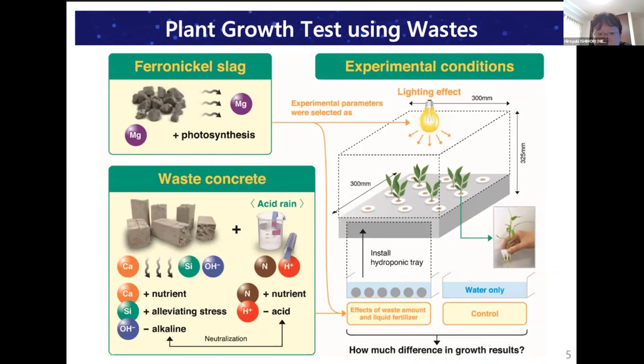Ferronickel slag has a lot of magnesium, which enhances photosynthesis. And waste concrete has a lot of calcium and silica as nutrients. Also, a lot of alkaline is included, so acid rain is co-used to neutralize the pH. Therefore, experiment conditions are changed: changes of lighting levels and waste amount, namely nutrient concentration level.